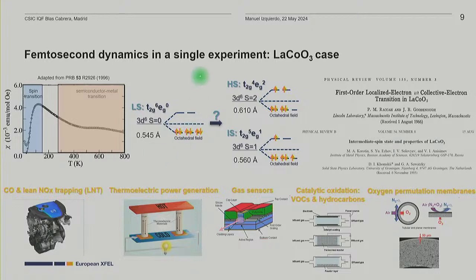At low temperature, everybody agrees that the system is in a low spin configuration. Basically, you have all the T2G orbitals full and the EG completely empty, and the ionic radius of the cobalt 3+ in this low spin configuration is 0.545 angstroms. Then a first model was proposed by Goodenough and Raccah: the transition has to be from low spin to high spin, so a spin 2, with 4 electrons in the T2G orbitals and 2 electrons going into the EGs, which results in a much larger ionic radius.